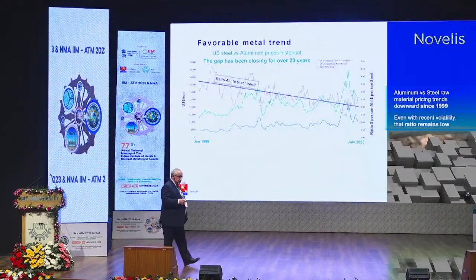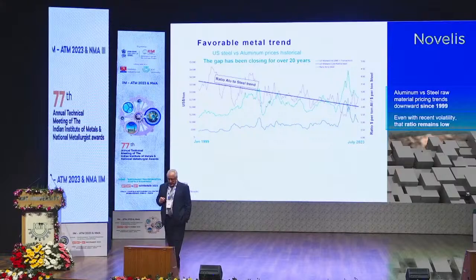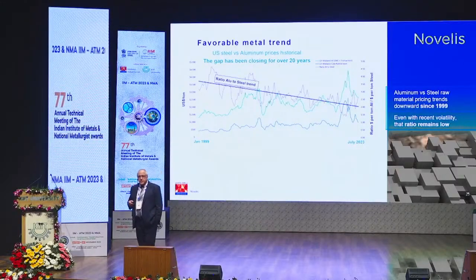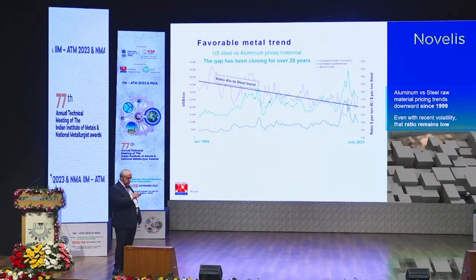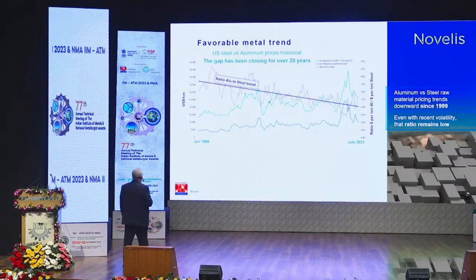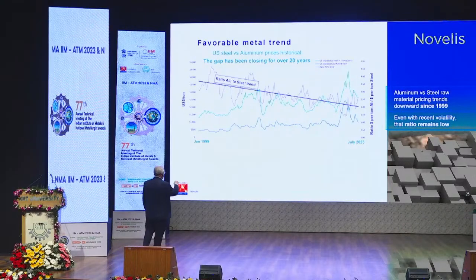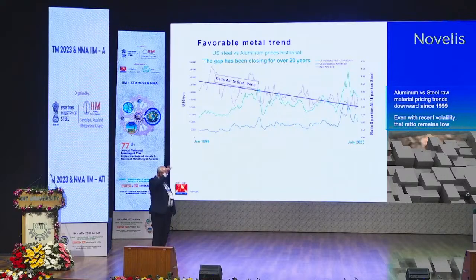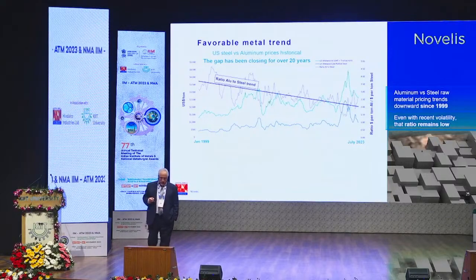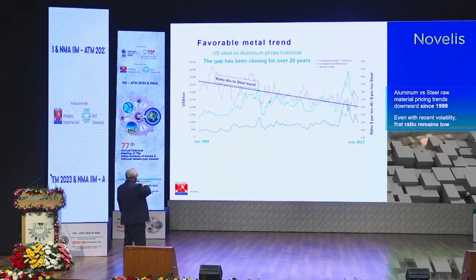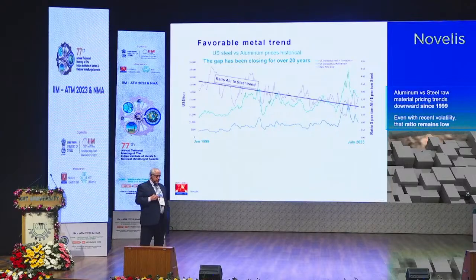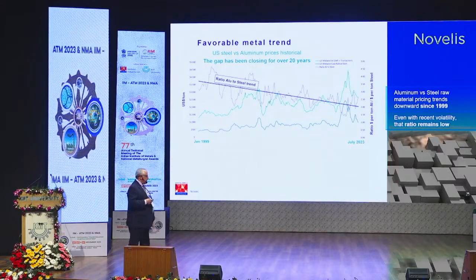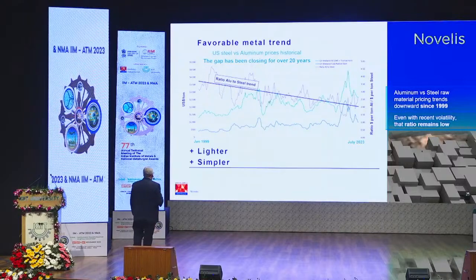And my last point will be about the economics. We hear a lot about the price of aluminum against steel, but if you dezoom a little bit, that's a very interesting curve which shows the evolution of price between steel and aluminum, not with these peaks up and down, but the global trend, which you see here, ratio aluminum over steel. And you see that over time, this ratio is going down. So we're not at all in a perspective of having aluminum more expensive as compared to steel in the future. It's exactly the opposite. So that's a very healthy base.